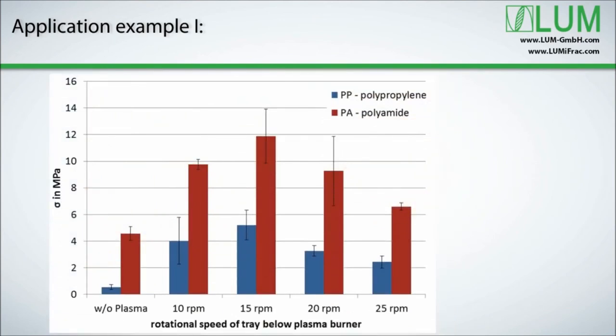The diagram shows the influence of different treatment conditions. The tray was rotated with 4 different speeds, which can be seen on the x-axis. PP, which has a lower surface energy, 32 millinewton per meter compared to PA, 43 millinewton, always shows lower strength. Even after plasma treatment, the ranking of the polymers used is the same as before treatment.